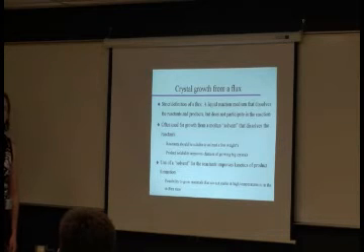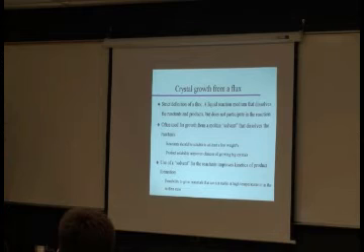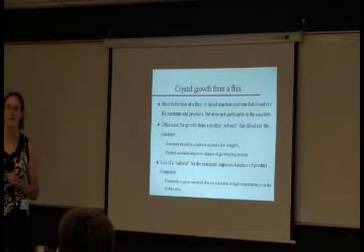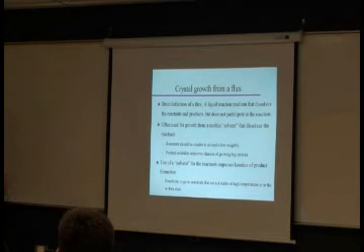Now, the good question is, how soluble do they have to be? Some people say, oh, you need high solubility or you'll never be able to make crystals. It's not true. If you have a few weight % solubility, you can often make crystals. The advantage is you have some of your reactant in the dissolved state. It can react, and of course, according to Le Chatelier, we will dissolve more of our reactant. So we will slowly dissolve it. It might actually help us control our reaction rate. Okay?